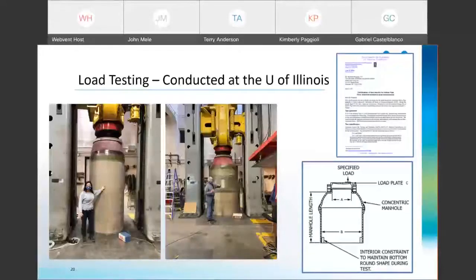The ASTM standard requires that the manhole be long enough to include at least one of all unique or repetitive features. In any case, the minimum length of the manhole cylinder shall not be less than 36 inches. In the case of both manholes tested by Hobas, the total length was 10 feet, well above the requirement.